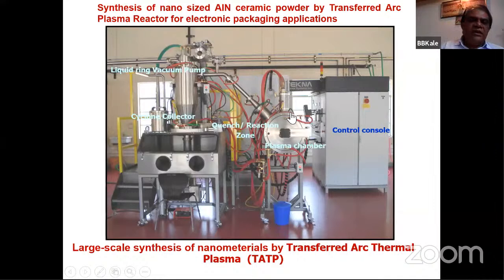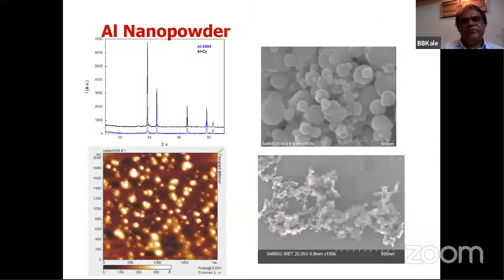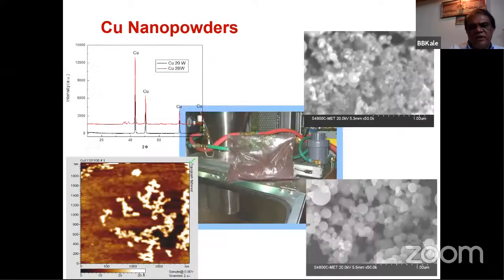We developed it with Tekna, Canada. This is aluminum nanopowder we developed in this. You can see a very sharp peak. This is a very sharp peak because these aluminum particles are highly crystalline. Though they are smaller particles, they get agglomerated. When you disperse them, they will separate again. Here you can see the bigger balls, where many particles come together and form this kind of ball, which we can observe in the transmission electron microscope.